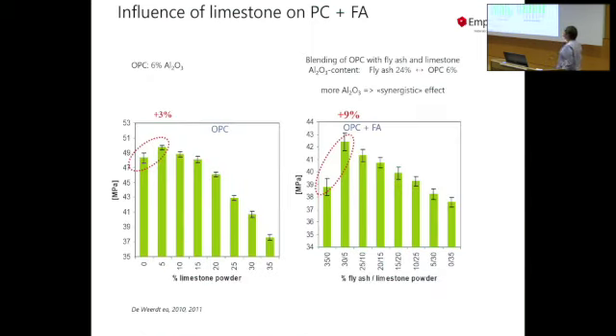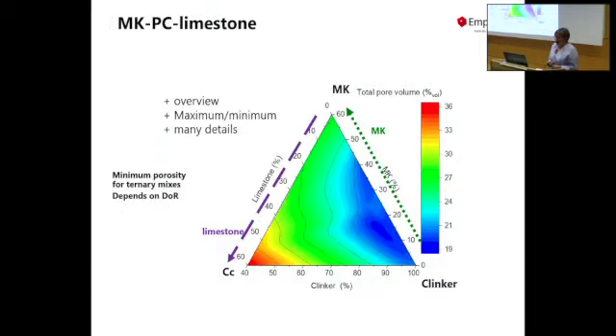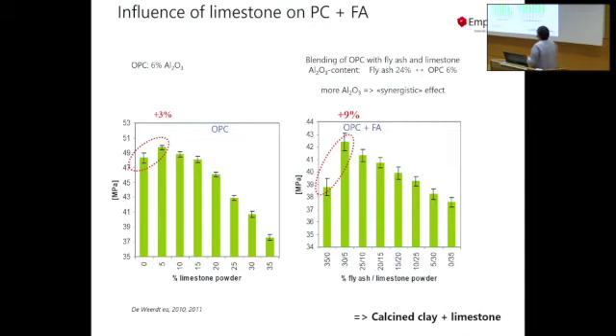Maybe if we just compare here the strength gains of a Portland cement and the Portland cement fly ash limestone blend, you can see you can get quite nice strengths if you mix them properly. And this was a replacement, 35% replacement. And maybe just one last word on that. The same trick is also for the so-called LC3 or limestone calcined clay cement. You just use, instead of fly ash, calcined clay to give you more aluminium, and then you balance it nicely with the limestone to optimize the amount of ettringite you might form.